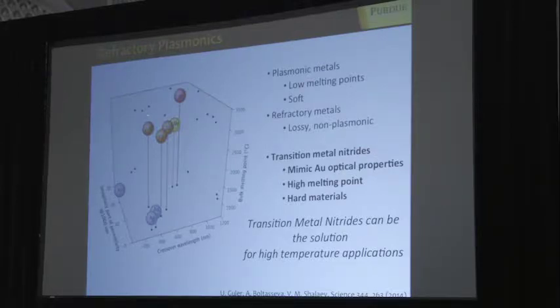But in that regard, look at the transition metal nitrides, such as zirconium nitride and titanium nitride. Look, they are plasmonic. The real part of the dielectric permittivity becomes negative in the visible. So they are plasmonic materials, but they're also very much temperature stable. They're as refractory as tungsten is. So they take advantage of both worlds. This is to be compared to silver and gold, which have a very low bulk melting temperature, around 1,000, but as I pointed out, when you nanostructure them, problems start even at 350 Celsius. So that's the idea: to use these transition metal nitrides, which are refractory, can sustain high temperature, very robust materials, but also are plasmonic.